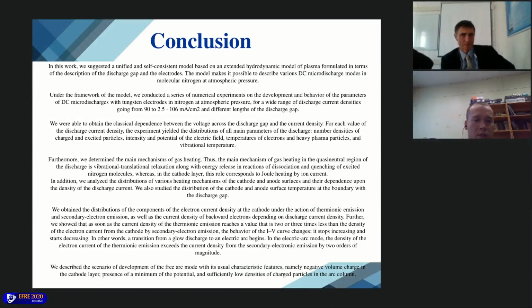And on this slide, some conclusions. In this work, we suggest a unified and self-consistent model based on an extended fluid model of plasma, formulated in terms of the description of the discharge gap and the electrodes. The model makes it possible to describe various types of DC discharge modes in molecular gases, for example, in nitrogen at atmospheric pressure. Within the framework of the model, we conducted a series of numerical experiments for this interval of current density.